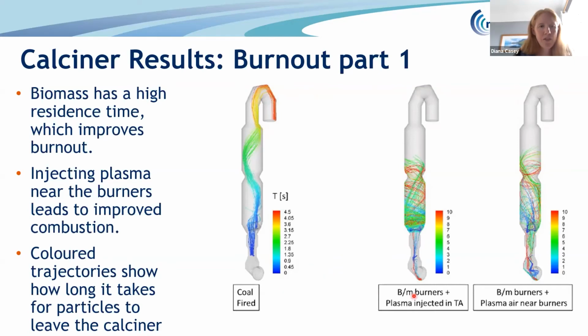The fuel switch images look quite different to the coal base case. The coloured trajectories show how long it takes for the particles to leave the calciner. Biomass has quite a high residence time, which improves the burnout of the particles. We found that injecting the plasma near the burners, shown in this one, leads to improved combustion. You can see the lines are a lot more blue, showing a shorter residence time here than they are here.